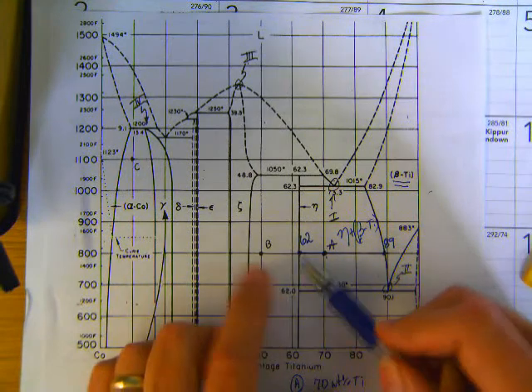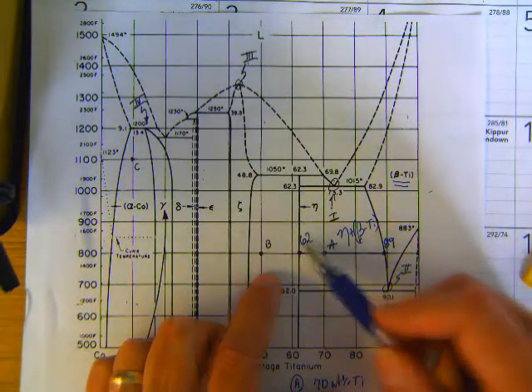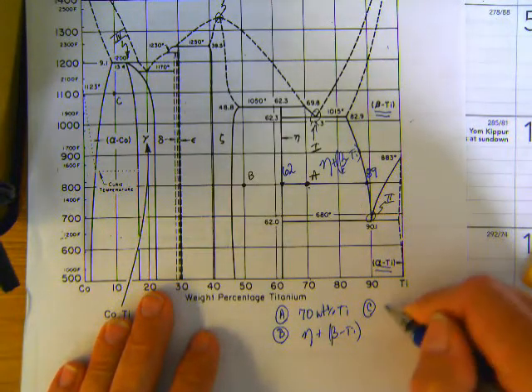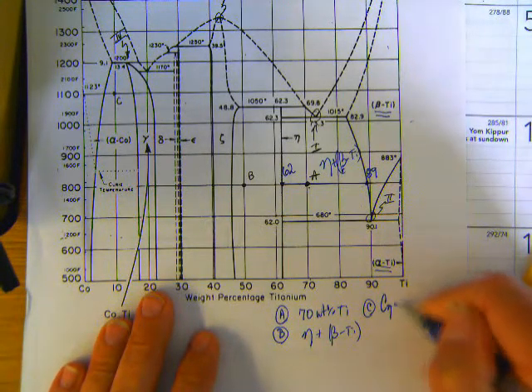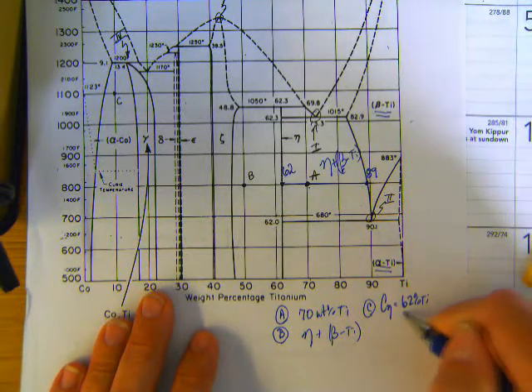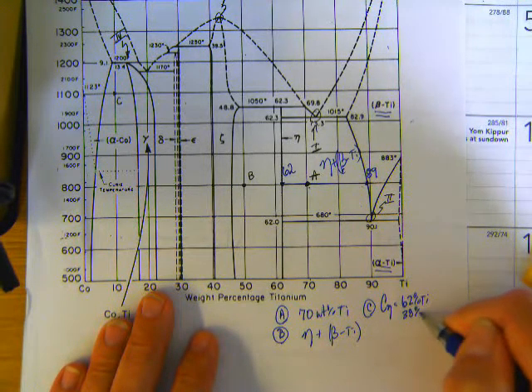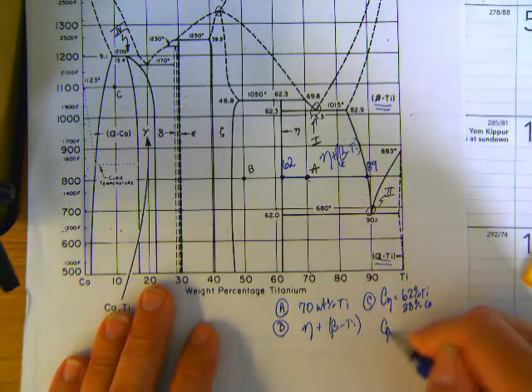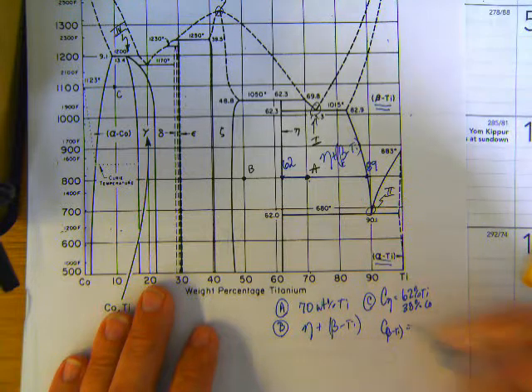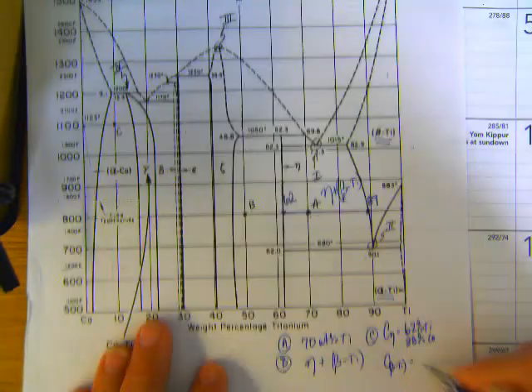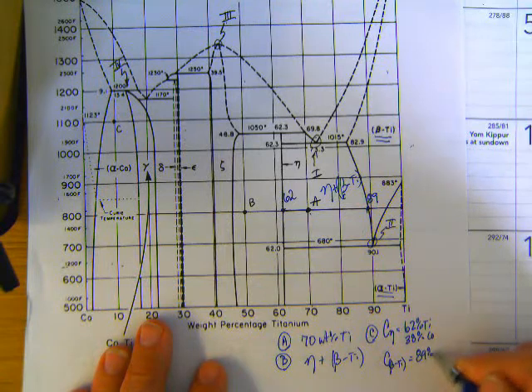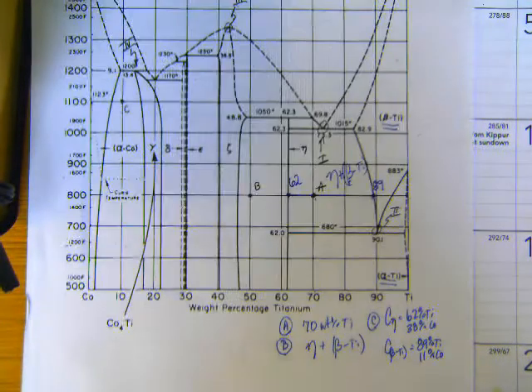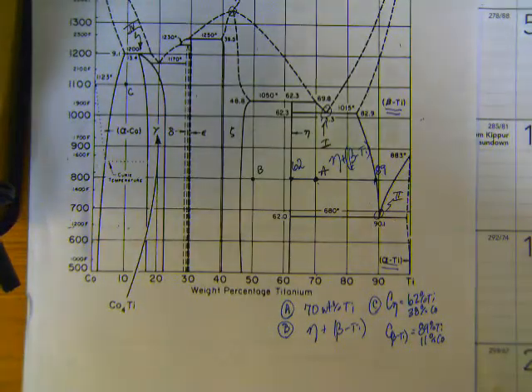So the composition of the eta phase only can be 62%. So if we come down, we would say for our third piece of information, the composition of the eta phase is 62% titanium. Obviously then it's 38% cobalt. Similarly, the composition of the beta titanium phase is 89% titanium and 11% cobalt.